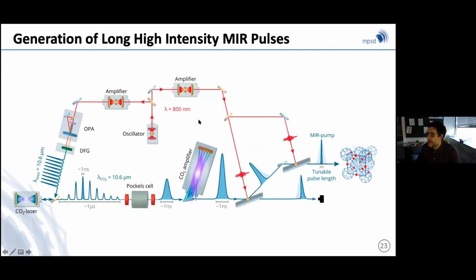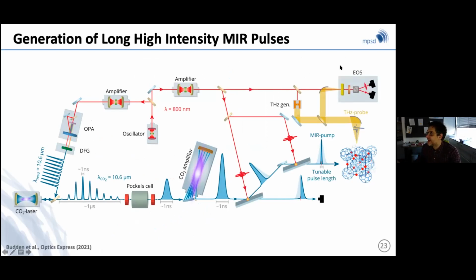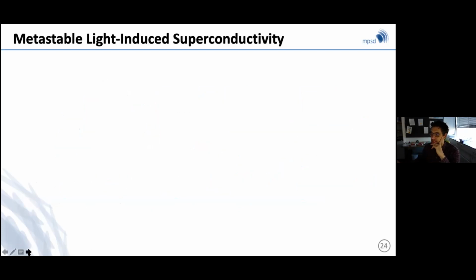And so what we could do, again, is develop a new laser source that could drive the system using pulses that could be tuned between a couple of picoseconds and a nanosecond, and which could then be coupled with conventional Terahertz technology, so that we could again use the same mid-infrared and Terahertz techniques to go search for these superconducting gaps in the spectral regions where Matteo saw the short-lived opening of the putatively superconducting state. So this is, again, conceptually straightforward, but technically not so. And Matthias worked very hard at developing this source.